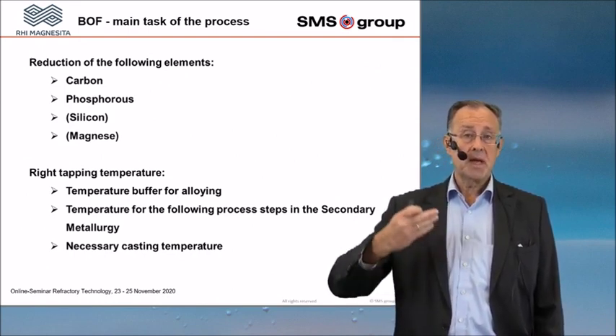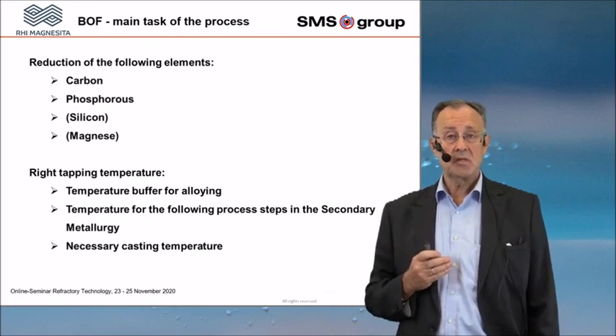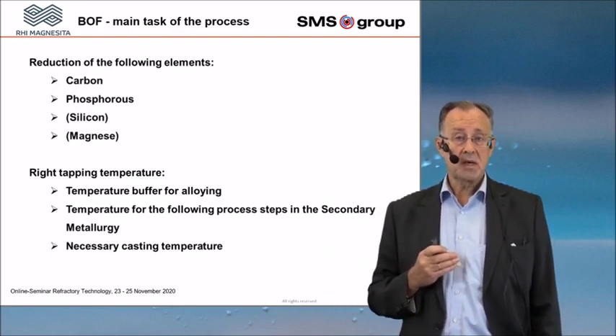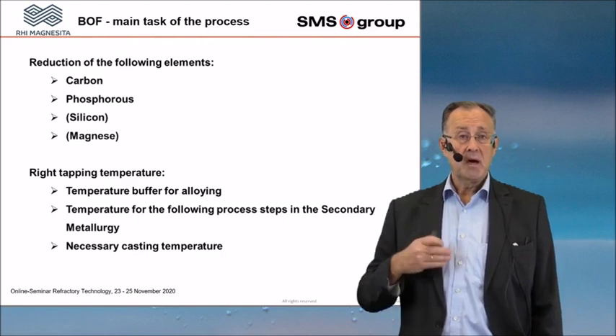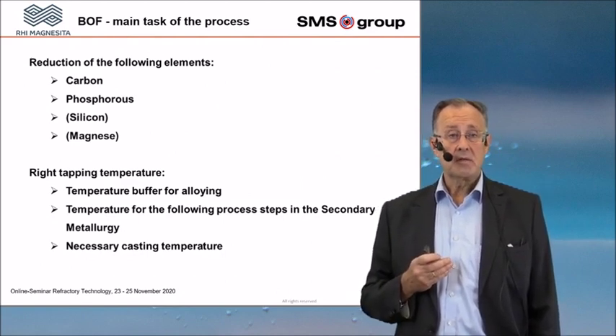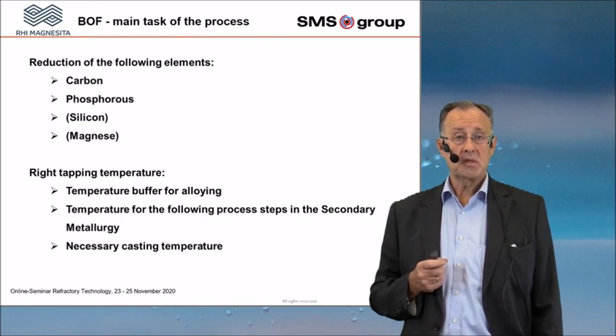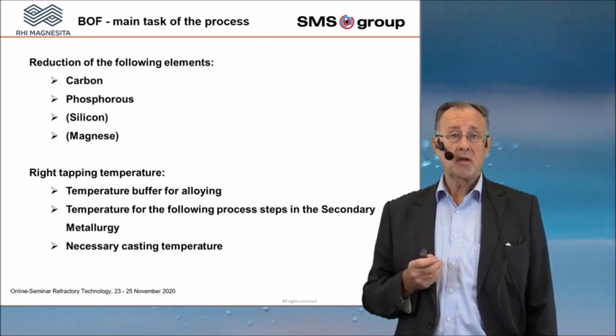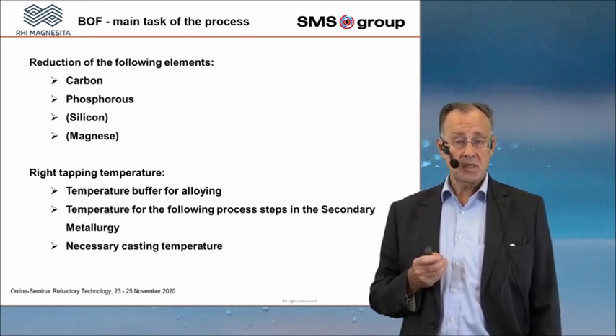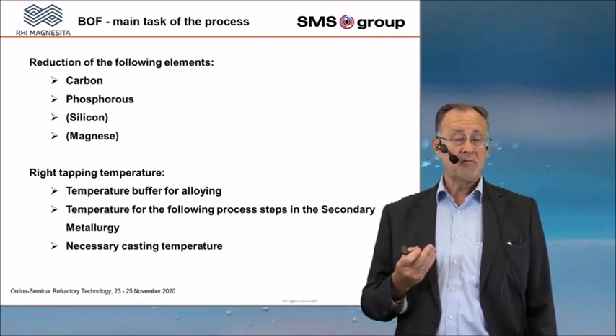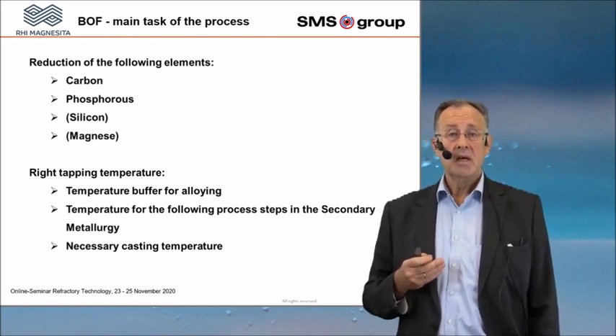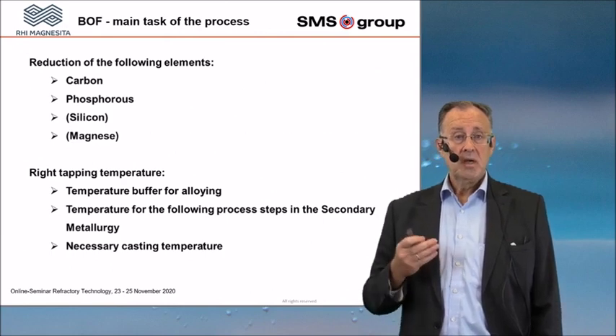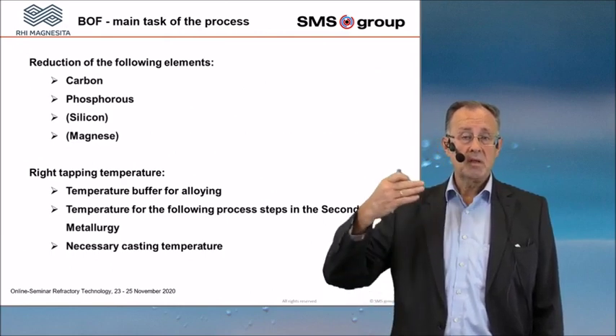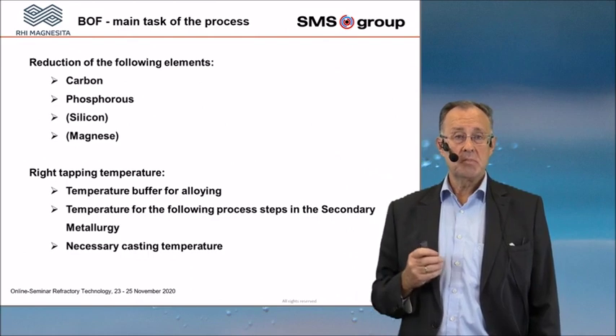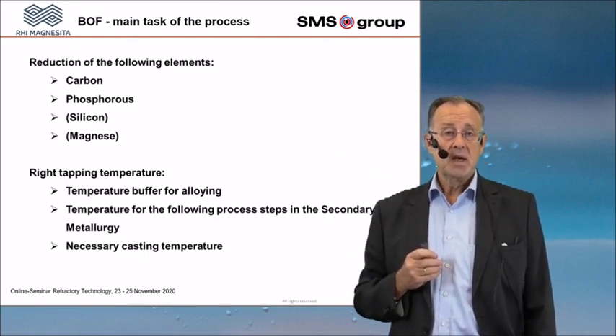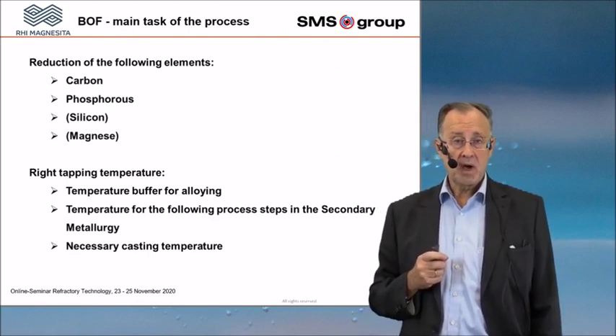All the treatment steps behind the BOF need a certain temperature, because there is a temperature consumption. Yeah, when you add alloys in your liquid metal bath, then you are losing temperature. You need temperature for all the process steps in the secondary metallurgy. For example, when you have a vacuum treatment behind, it is temperature consuming. So that means you have to put all the additions for all the treatment steps behind the BOF process in the tapping temperature of the BOF.